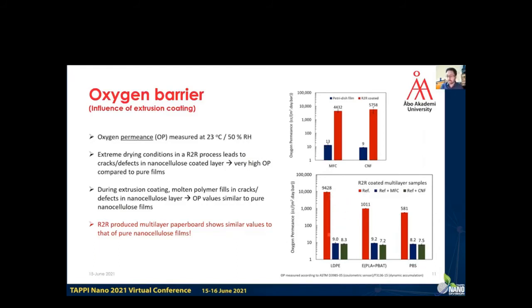So here we have 3 sets for 3 different extrusion polymers: LDPE, Ecovio, and PBS. The red one is for just the polymer, and then the blue is when they have MFC as a multi-layer structure, and then the green one is when they have CNF as a multi-layer structure. One can see that the polymers, the thermoplastics as such, do not have any oxygen barrier or have very high permeance. As soon as we have a multi-layer structure, the oxygen permeance falls down, and these values are very, very close to what we get for the pure films.